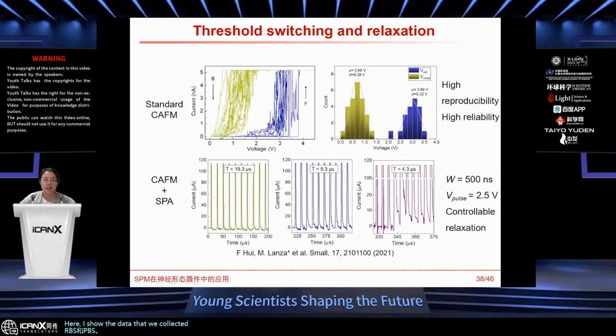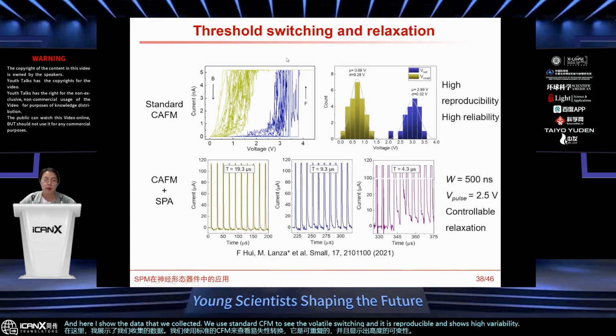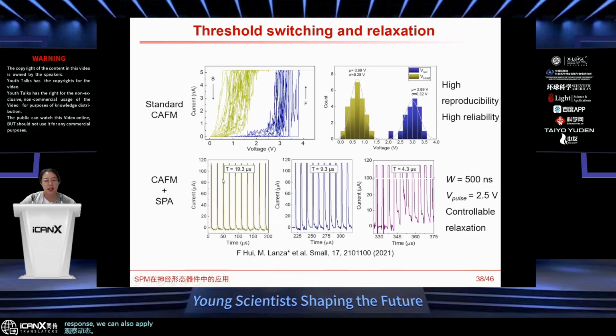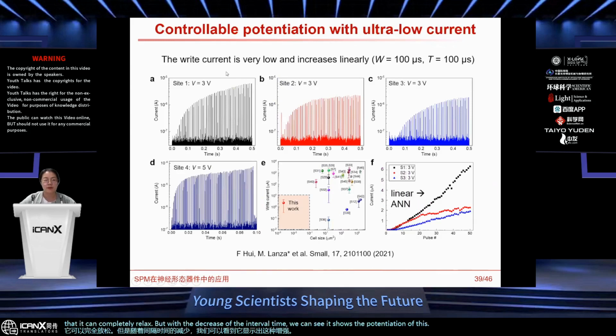We use standard C-AFM to see the volatile resistive switching, and it is reproducible and shows high reliability. To observe the dynamic response, we can also apply the pulse voltage stresses. Here we tried different pulse interval times, and we see a controllable relaxation. When the interval time is large, you can see that it can completely relax. But with the decrease of the interval time, we can see it shows the potentiation of these samples.